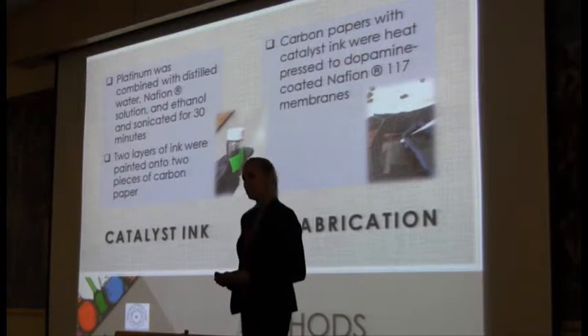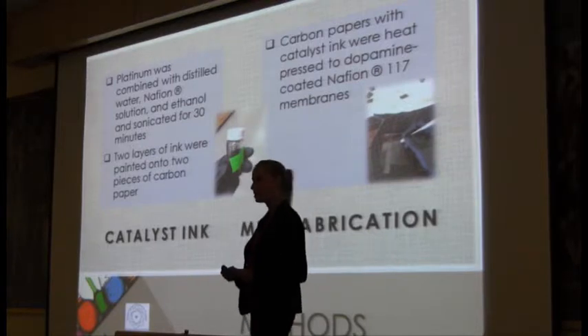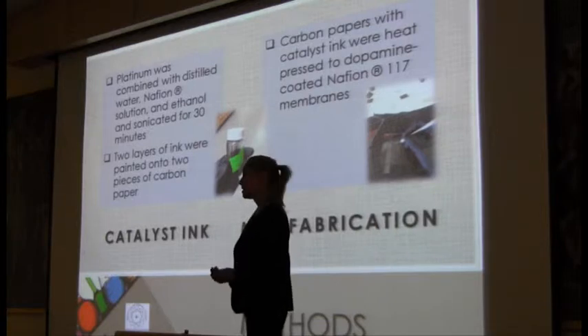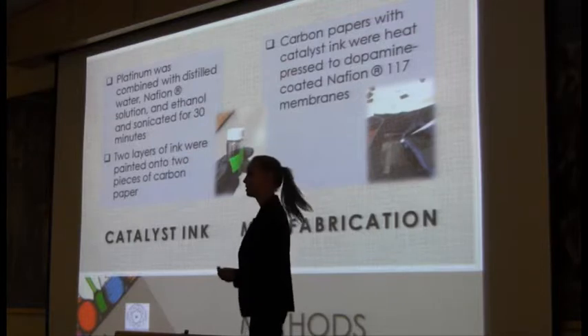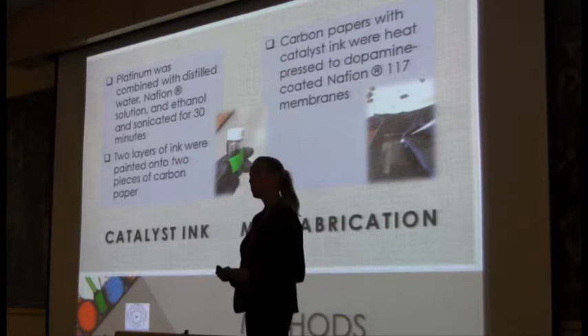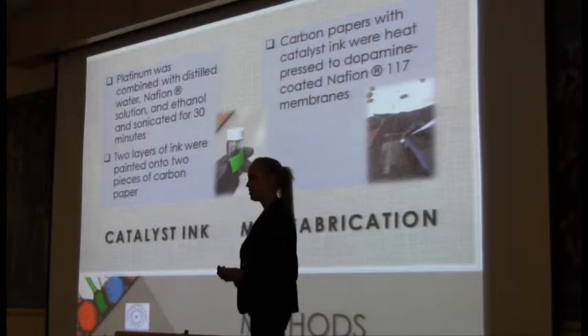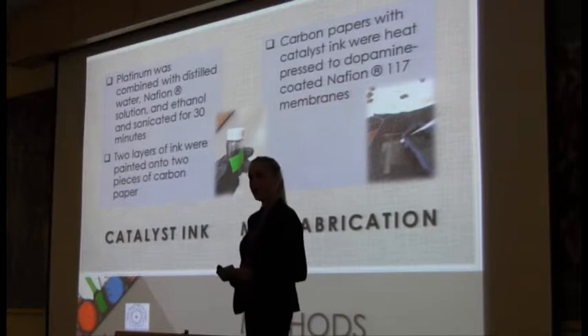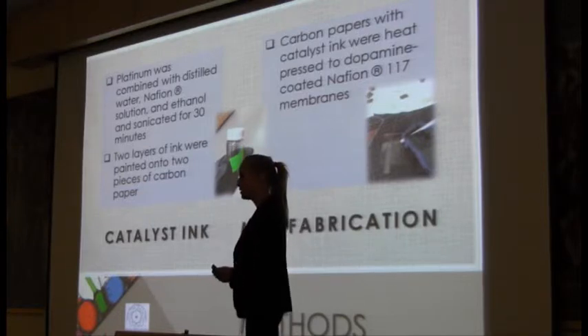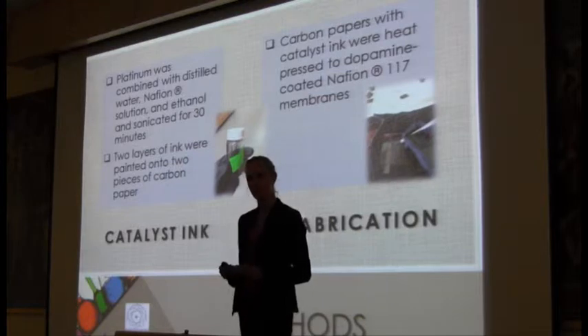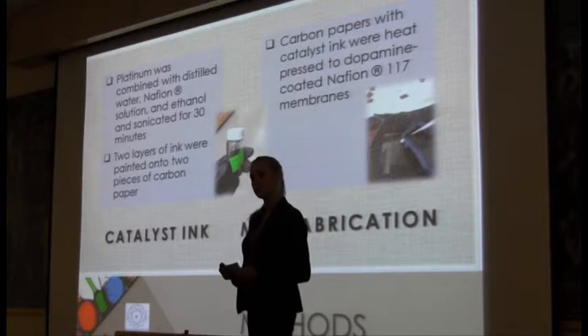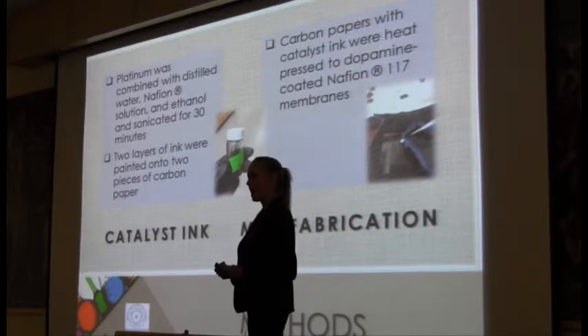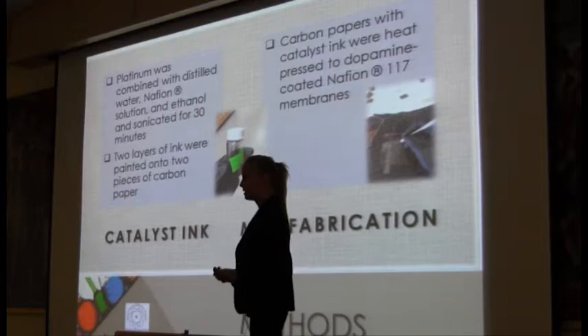To create the catalyst, we made a platinum ink with ethanol, Nafion solution, and platinum. We sonicated it for 30 minutes. Sonication means that we use vibration to separate particles. It was stored in a sealed container until further use. We painted the ink onto 2 pieces of carbon paper that we cut into 5 square centimeter squares. 1 layer of ink was painted onto one side of each carbon paper. It was allowed to dry for 1 hour, and then 1 more layer was painted on. These carbon papers were heat pressed to the dopamine-coated membrane at 135 degrees Celsius and 80 psi for 90 seconds.